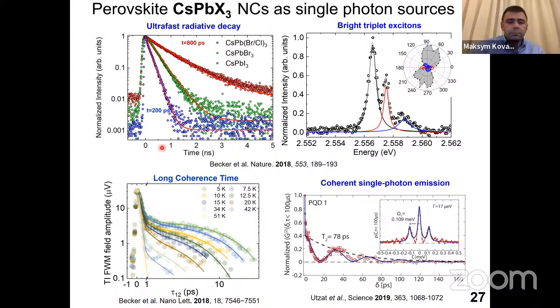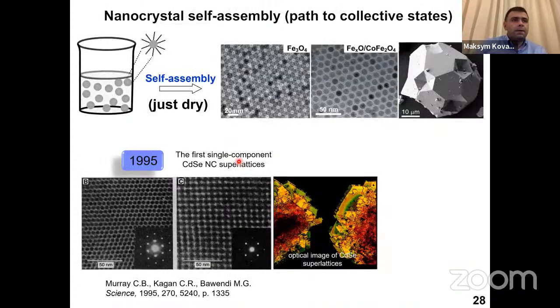And so here again, we look at the history where people have used a drying mediated self-assembly of nanocrystals to generate long-range ordered superlattices. You simply can take a monodispersed colloid of nanocrystals of spherical shape. You can dry out the solvent and you will end up with a superlattice. This is known for cadmium selenide for several decades now.